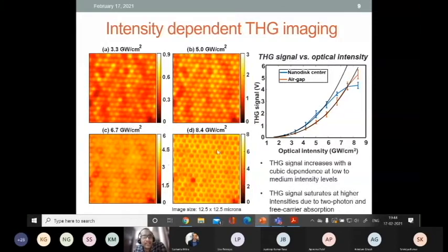What you see here is that we vary the intensity of light and we see these interesting patterns. At low intensities, it's the nanodiscs which light up. As I increase the intensity, it's really the outside regions which tend to light up. So the contrast gets inverted. Why does this occur? It's because the silicon nanostructures are somehow saturating in terms of their nonlinear signal because of multiphoton absorption and free carrier absorption type processes. And the onset of them is very different as you excite the center of the pillar versus outside the pillar.